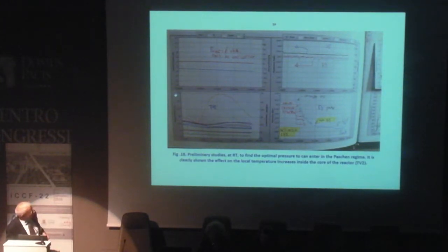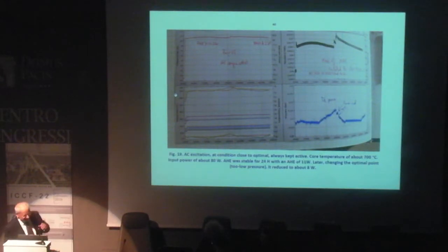In this experiment, the wire temperature was about 700 degrees, at a power of 80 watts, and we get a stable excess heat of about 11 watts, until we change the parameters a little bit to check the resistance. So we have the loading of the wires and the excess heat decreased, but still active, at about 8 watts, so more than 10%. So it's very, very critical. The window of operating is very, very narrow.